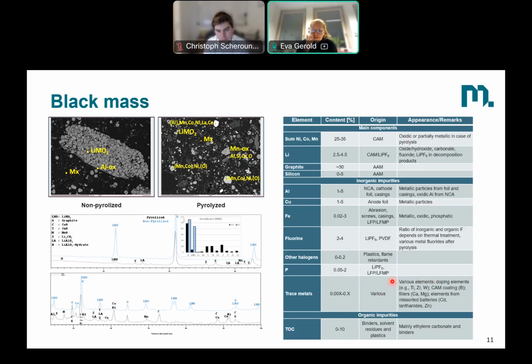And then we also have organic materials in there, especially binders and solvent residues, up to 10%. Of course, very dependent on the pre-treatment of your black mass. If you have a thermal treatment, the organics are quite low, so below 1%. If you don't do any thermal pre-treatment, and that's actually the way in Europe it is done quite often, you still have up to 10% of organics in there.